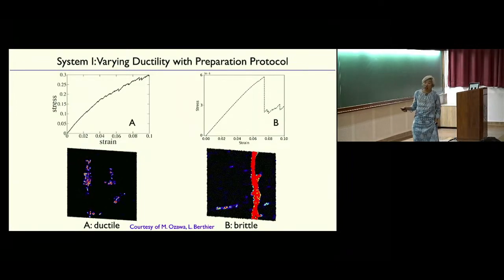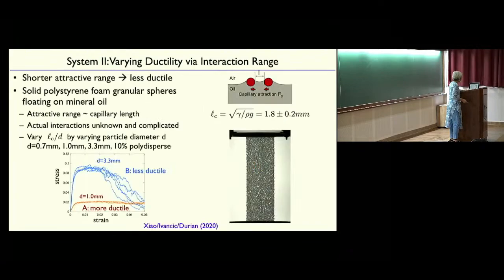But if you equilibrate at an extremely low temperature before quenching down to zero and shearing it quasi-statically, you find very different behavior. It's quite elastic up to a very high stress, and then bam, there's a huge rearrangement. The system develops a shear band, and then it starts to flow. That's what's called brittle behavior. You see the strain localization. So that's the system prepared in two different ways, from a high temperature quench or a low temperature quench.